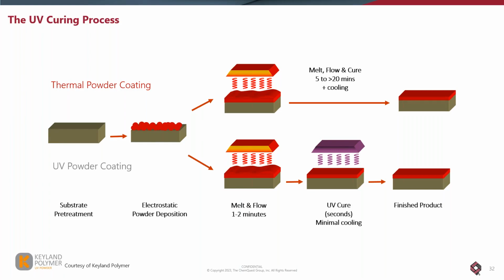But if we want to compare it to a thermoset powder coating process, basically powder is applied to a substrate with a thermal cure, or thermoset powder coating. You heat the substrate, you heat the coating, you kick over the cure mechanism, and you get your melt flow and hardness, and your part's coated. With UV cure powder coatings, you separate the cure mechanism from the heat, basically. You're going to rely on ultraviolet light to get the cure.